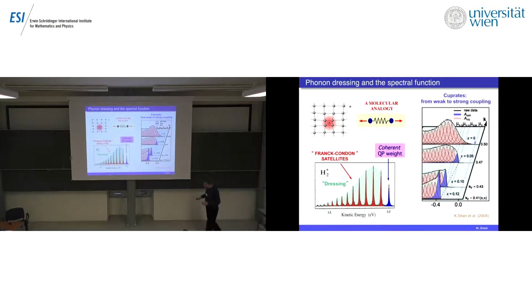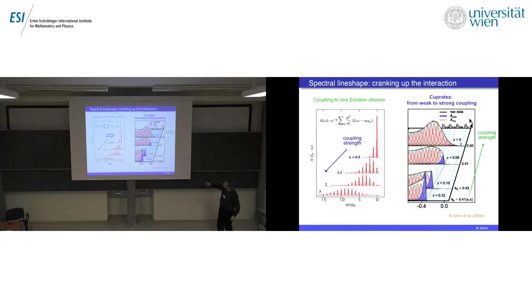Now, not only the dispersion is affected by the coupling, but also the line shape. The spectral function gives you the line shape of the spectrum, and therefore, as a function of the strength of the interaction, the line shape will change. These are examples, I wanted to show this directly. Yeah, this is what you may expect to see from a coupling to a single phonon, as a function of the strength of the interaction. So with moderately weak interaction, you have a strong quasi-particle weight and some satellites. And as the interaction is increased, spectral weight is transferred away into the incoherent part of the spectral function.